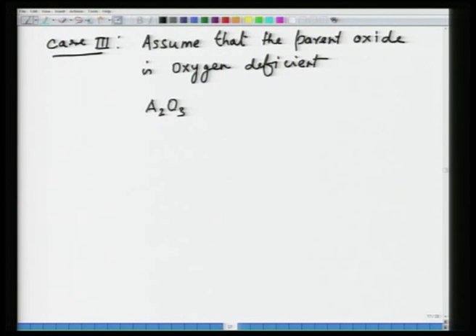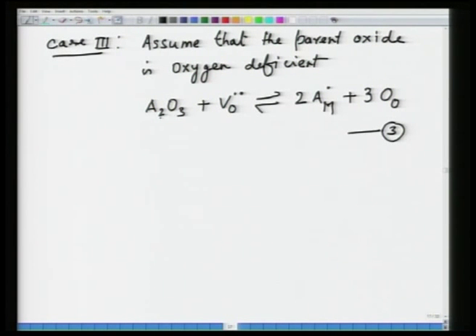Now, you have A2O3 going into the MO lattice, plus you had V_O present there. Now, what is going to happen to these V_O? So, both the metals, the 2 A's, go to M site. Since you had 1 oxygen site already vacant and you are going to create 2 more, all the 3 oxygens occupy oxygen site. So, the oxygen vacancy which was present in the solid to begin with has taken care of 1 extra oxygen. As a result, you do not create any other defect in the material. So, this would be case 3. Here it is balanced site wise as well as charge wise. You have 2 positive charges on the left and 2 positive charges on the right.